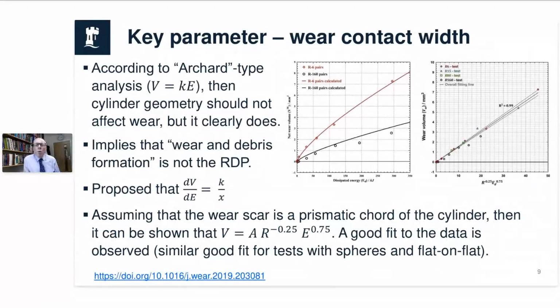But what we did notice is that we conducted tests with both cylinders with 6mm radius, so really quite small cylinders, and very large cylinder radii of 160mm. We used everything else the same though. And if Archard was relevant in that way, so Archard in very broad terms, or a derivative of Archard, the energy version of Archard, says that the wear volume will be proportional to the energy dissipated in the test. And if that was true, it shouldn't make any difference what size your cylinder is.